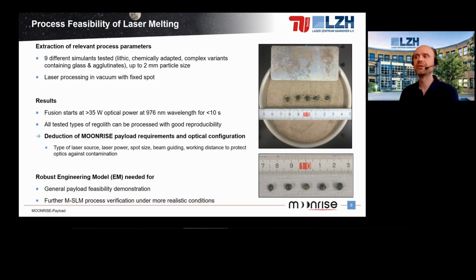with good reproducibility with the laser. From this, we deduce the MOONRISE-payload requirements and their optical configuration. So the type of laser source, for example, the laser power, the spot size, beam guiding, working distance to protect the optics against contamination. With this knowledge, we built a robust engineering model, on the one hand, to show that such a payload is generally feasible, but also to further investigate this MSLM process under more realistic conditions.